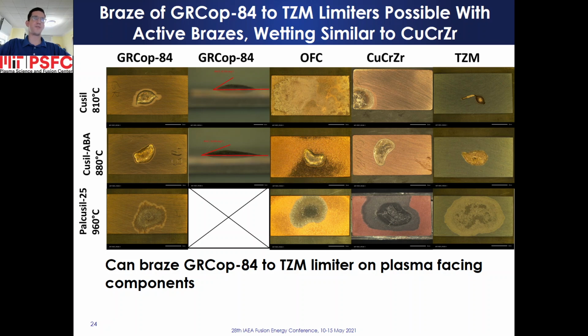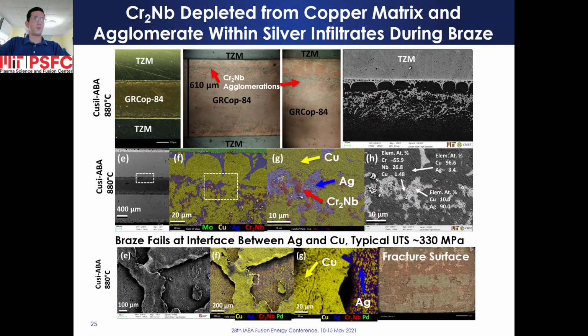GRCop-84 has similar brazing and wetting properties to copper-chromium zirconium alloy. During brazing of GRCop-84, chromium niobide precipitates are depleted from the brazed diffusion zone and agglomerate within the silver infiltrates, as shown in optical micrographs on the top row and EDS mapping in the middle row, leaving an interface between silver and a nearly pure copper layer. Brazes subsequently fail at the copper and silver interface, as shown at the bottom row, at an ultimate tensile strength of 330 megapascals. This is suitable for brazing TZM limiters onto the launcher face. Future developments of diffusion bonding may result in higher tensile strengths.